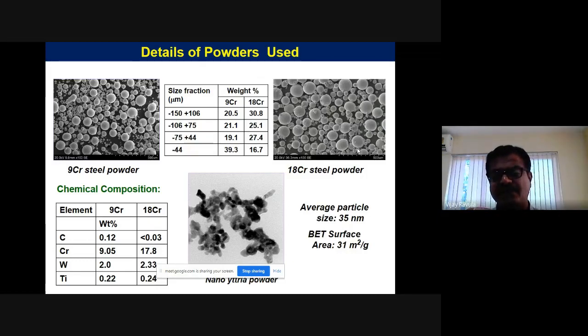We can see the 9 chrome steel powder and the 18 chrome steel powders, and the typical chemical composition is given here, and the size fraction analysis is given here, all of which we produced. These are the materials we produced in-house and then used. And this nano yttria we have purchased, with a particle size of around 35 nanometers and a surface area of around 31 square meters per gram.